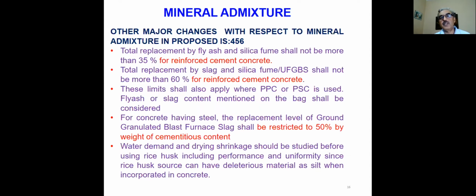Other major changes with respect to mineral admixtures in the proposed IS 456 are that the total replacement by fly ash and silica fume shall not be more than 35% for reinforced cement concrete. What happens is when we put fly ash in concrete, carbonation increases at a faster rate, which affects durability, so there has to be some limit. We put 35 because PPC is permitting 35 as of now. I would have preferred 30, but this is as of now agreed as 35.